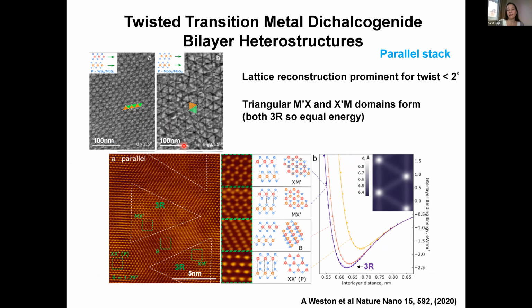And we can see that we get a similar type of triangular lattice reconstruction, where we have the more favorable 3R type stacking regions in large, and between them we have these dislocation type regions. We compare that to the modeling, and that makes complete sense. We understand that the 3R type stacking is the most dominant, and so we want to enlarge those regions.